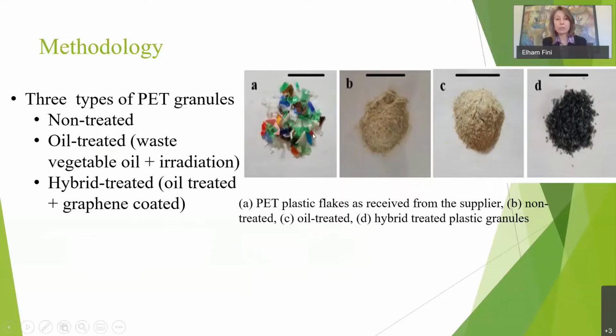So obviously someone may think, oh, why don't I just grind this mixed plastic first and dump it into the construction material? Well, the problem is segregation, because the plastic doesn't like cement or asphalt by itself, and they're going to separate. So as soon as you're mixing and placing it down, your plastic will go to one side and the rest of your material will go to the other side. You don't want that. You want a very nice homogeneous mix. And that's why we have to make the plastic like the rest of the material. And to do so, we use the oil treatment and in some cases, carbon coating.